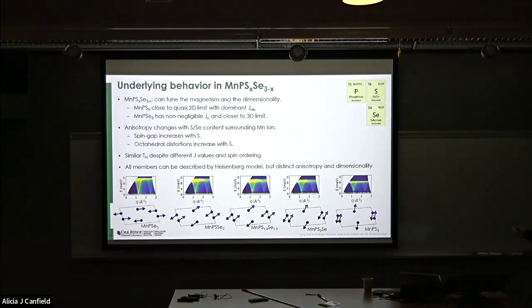You're changing sulfur to selenium, so you're increasing the ionic radius. Maybe you're changing the distortions of the octahedra a little bit, increasing the spin-orbit coupling a little bit. You're changing the magnetic anisotropy, and anisotropic exchange would be very sensitive to whether it's sulfur or selenium, because selenium has larger spin-orbit coupling. So you're changing the structure and the interaction strength, but the ordering temperature remains the same. That's a little bit of an unknown, why that still happens.